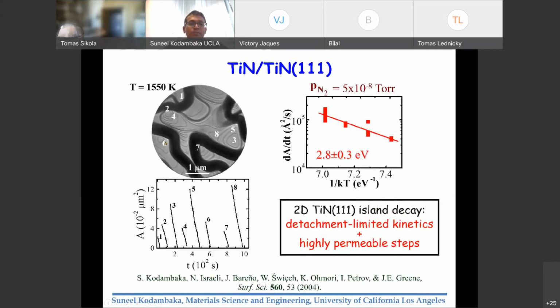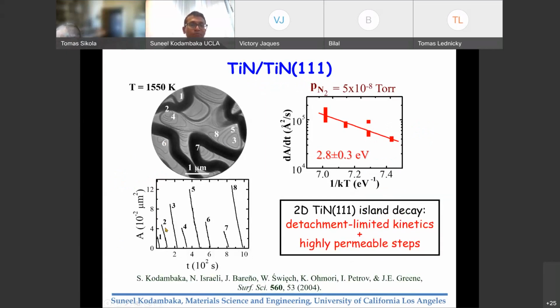From these types of measurements, similar to the STM data, we can measure the areas of these islands as a function of time. These are the plots of island areas as a function of time for different islands. And you see here a fairly linear decay behavior. But there are more details in here: one has to model this phenomenon. And what we find is that for titanium nitride in this wedding cake configuration, the atoms can diffuse much faster than overcoming an Ehrlich-Schwoebel barrier.